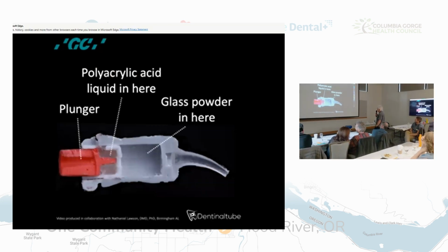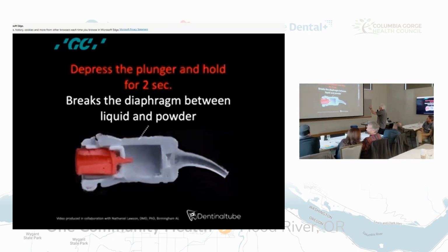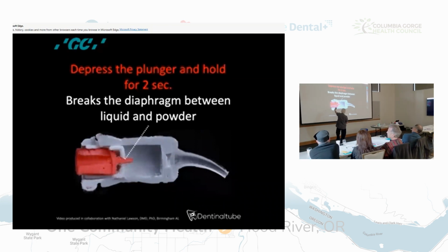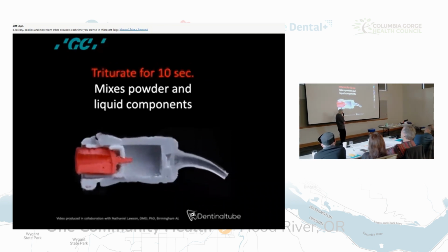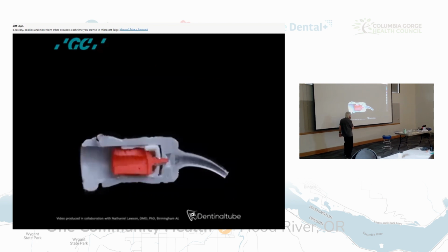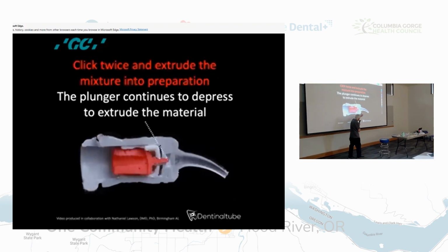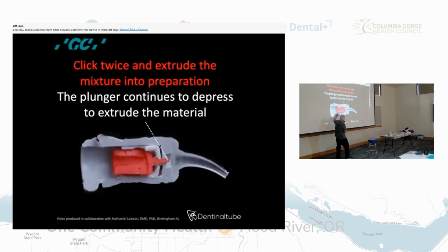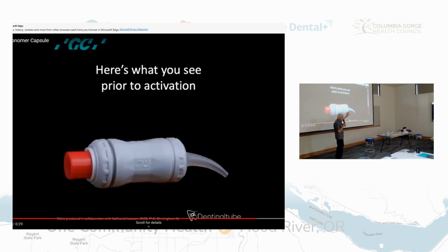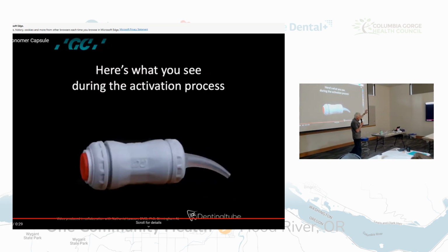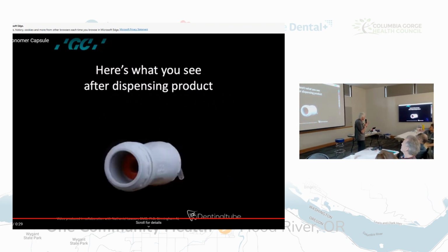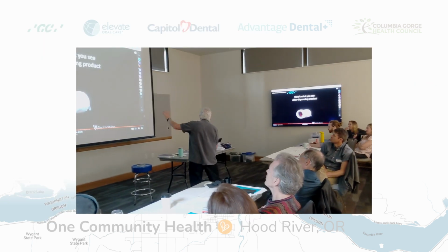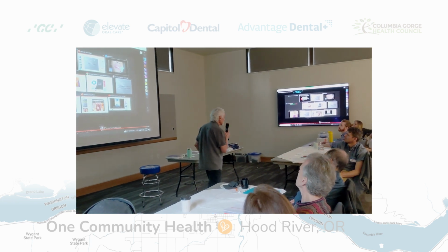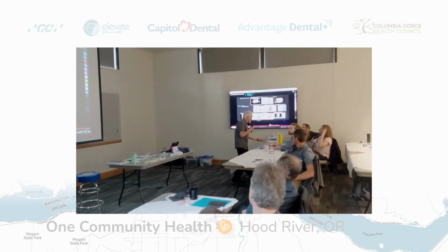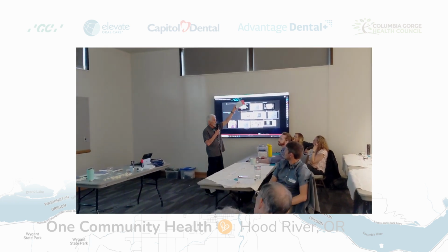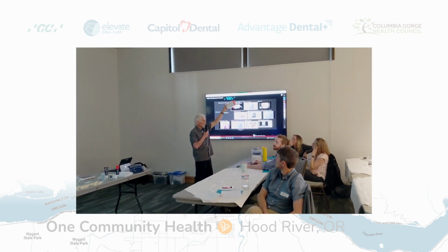Polyacrylic acid and glass powder. So it's separated by that, okay? When you hit the plunger, it punctures that diaphragm. You shake it, the two mix, you express it out. So there's two chambers. One has polyacrylic acid, and one has the glass. And the glass has been sitting on the shelf in a box, in this box, for how long? Who knows?